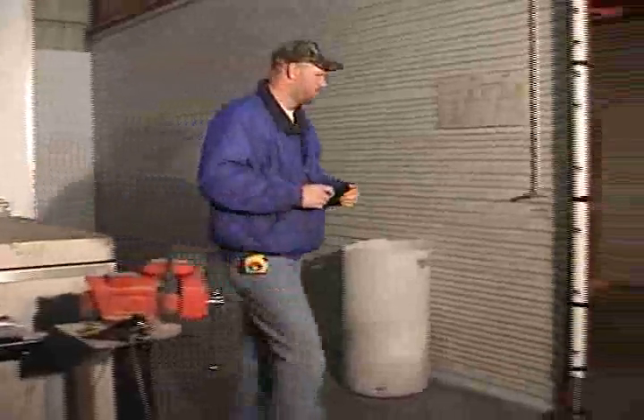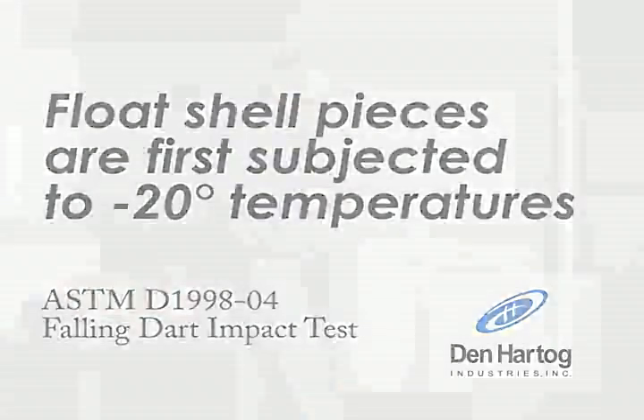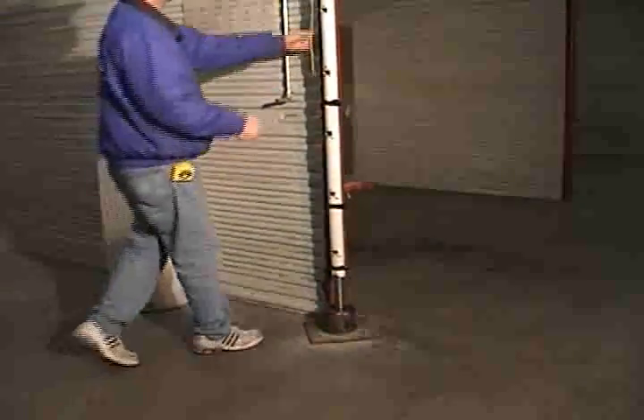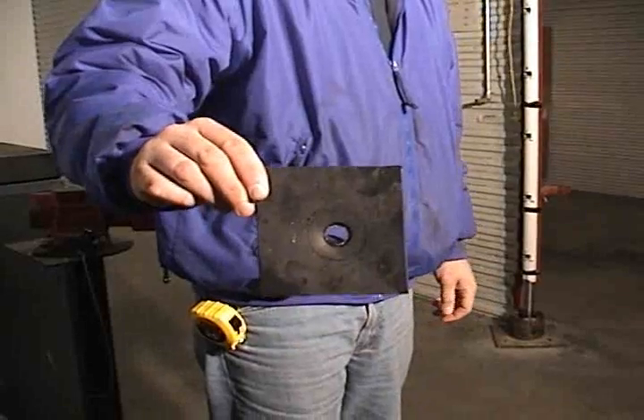Let's take a look at a couple of examples. One of the required tests for float quality is the ASTM D1998-04 Falling Dart Impact Test. This test measures the ductile failure of the float shell material at specific impact loads, and it is a test that float manufacturers should pass to deliver the best value. Let's start with an ACE float, first at 90 foot-pounds, which is the ASTM test minimum. The ACE float passes the 90 foot-pound test. The coupon shows no cracking.